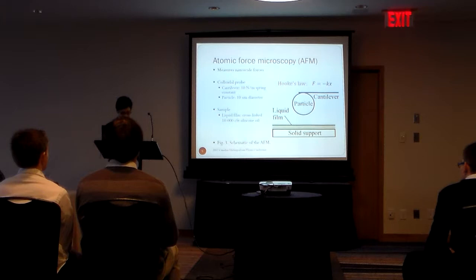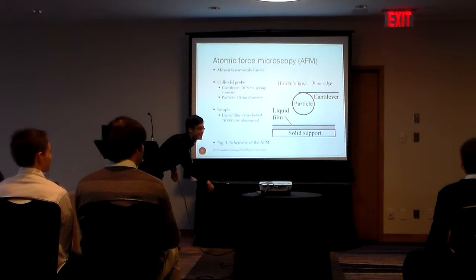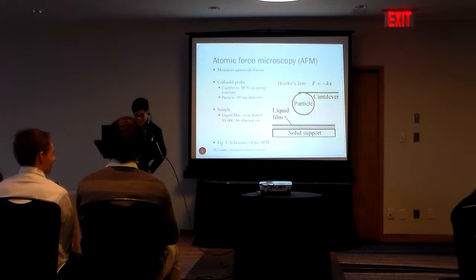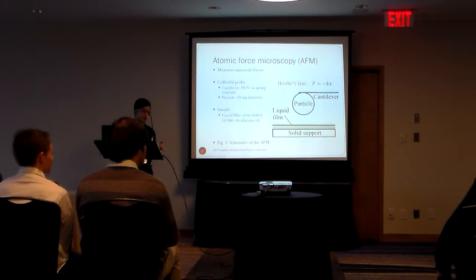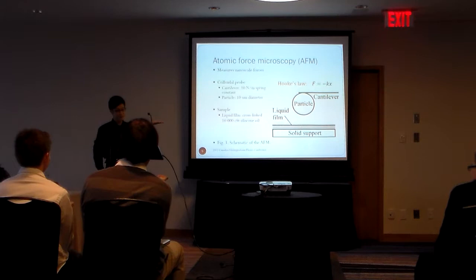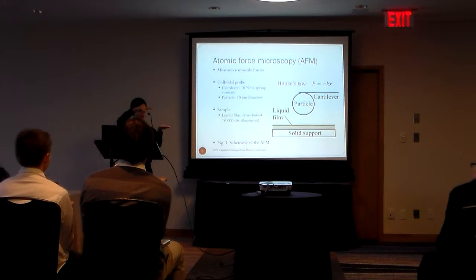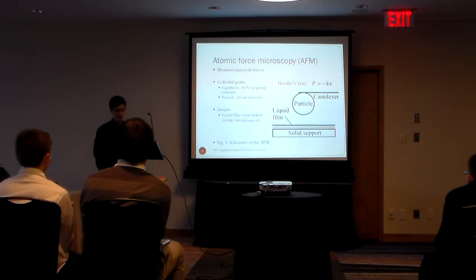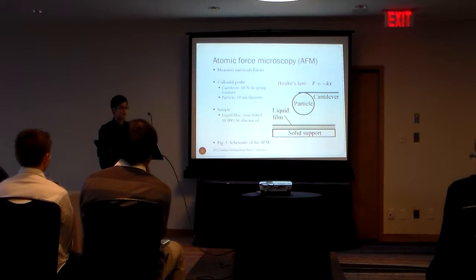I actually have some cantilevers here to pass around — please have a look. The cantilever is at the end of those silicon chips and they're only about 50 micrometers long, so you have to look very closely. To understand this figure, I want everyone to hold out their palm: this is your liquid film with the solid support underneath, and your finger is the colloidal probe. As it moves up and down on the liquid film, it will bend due to the interactions of the cantilever with the film. The distance that the cantilever bends is known, and the spring constant is also known, so we can calculate the force using Hooke's Law.